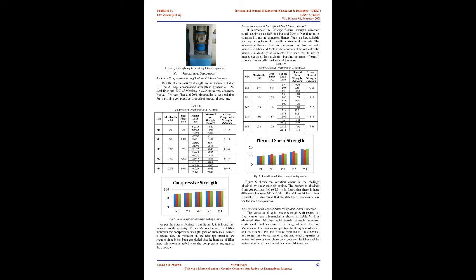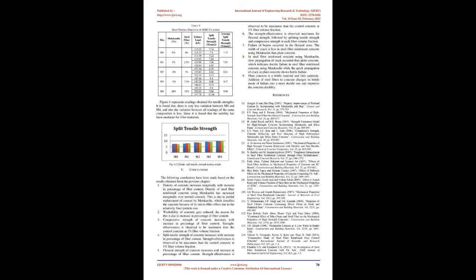The standard 150 mm cube specimen was used in the cube compressive strength test, and the methods and procedures of the ordinary concrete mechanical properties test method standard GB/T 50080-2016 and the test method for fiber concrete, CECS 13-2009, were referred to in conducting the test. Constant speed stress control was used in this test, and the loading speed was 0.6 MPa/s. The specimen would be automatically unloaded, and the strength of damage was recorded by the machine. The cube compressive strength testing machine is shown in the figure below.